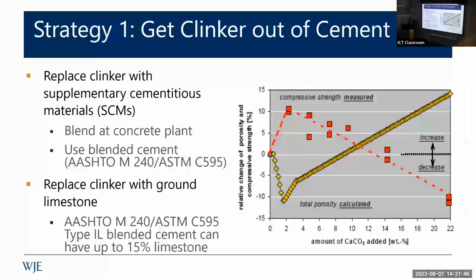So what has happened is the cement industry is responding. They're starting to blend limestone in with their clinker. And so this movement from, instead of just blending at the concrete plant SCMs like fly ash or slag, you're going to see more and more blending happening by the cement companies. They're going to start selling blended product. And this replacement, as I said, of the ASTM C595 type IL, it can blend up to 15%.